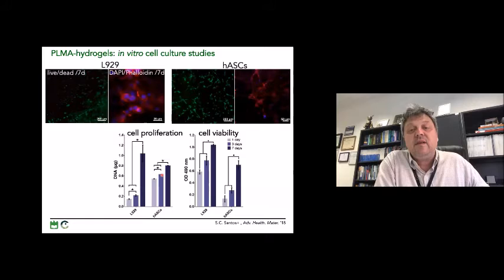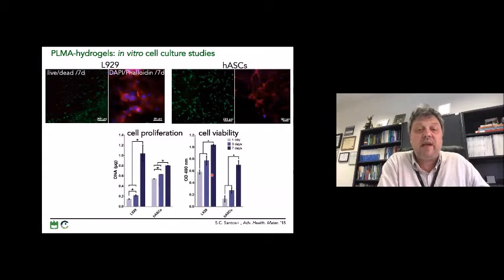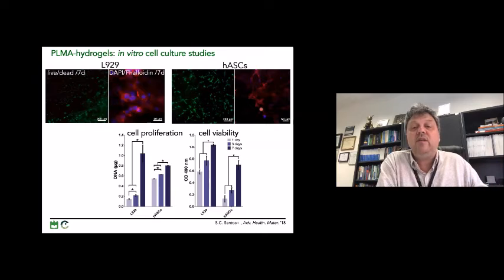So both cells exhibit very good levels of proliferation and viability, as seen by DNA and MTT quantification, up to 7 days, but we have results for much more time. The micrographs show that the encapsulated cells are spread and developed an adequate cytoskeleton organization, as you can see, for example, from this image, indicating a very good communication with the adhesive proteins of PLMA.